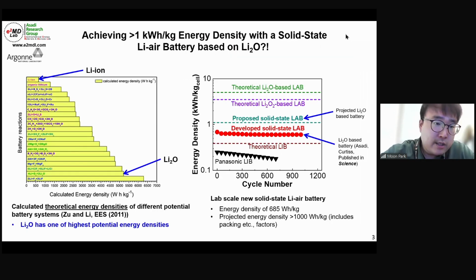This slide shows the introduction, a comparison of the lithium-ion and lithium oxide battery chemistry. The theoretical energy density of lithium-ion is around 700 watt-hours per kilogram. However, Li2O comes from the 4-electron reaction that can happen in the lithium oxide battery. I'll give more details about the chemistry in a later slide. It can show around 5,200 watt-hours per kilogram of energy density, which is very desirable for heavy-duty vehicles.